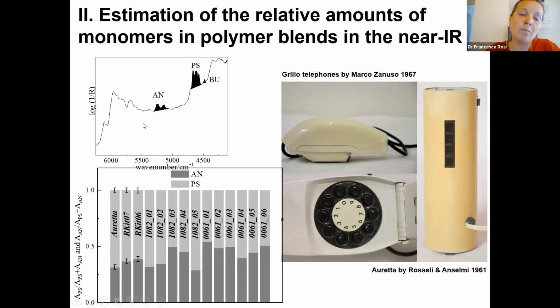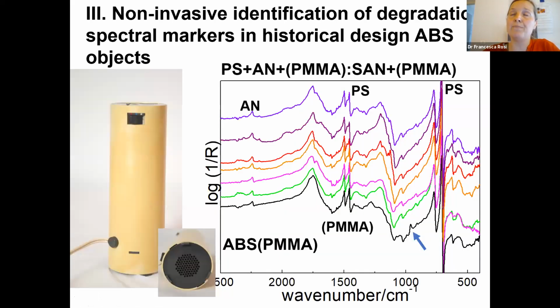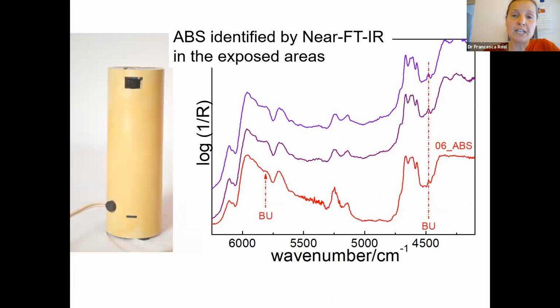In this case, by plotting the relative amount of acrylonitrile and polystyrene, we traced and evaluated the different polymers that compose the single elements of these two objects, the Grillophone and the Auretta by Rosselli and Anselmi, which is an air dryer. A further piece of information that we can give is linked to the degradation state of this plastic. I will show you some spectra recorded on this air dryer. By mid-FTIR spectroscopy, we were able to suggest that the plastic components constituting the different elements of the dryer were composed of a polymer made of polystyrene and acrylonitrile, given the absence of butadiene as in ABS. On the contrary, by looking at the near-infrared spectra, we clearly see that in the same point we have all three components, meaning that we also have butadiene, and so suggesting the presence of ABS resin.